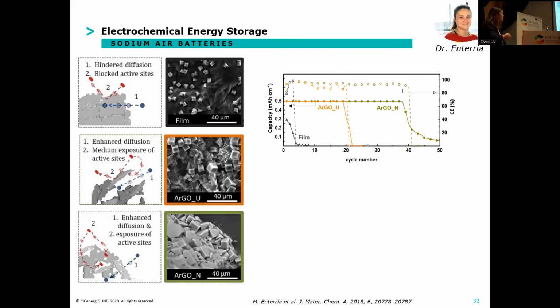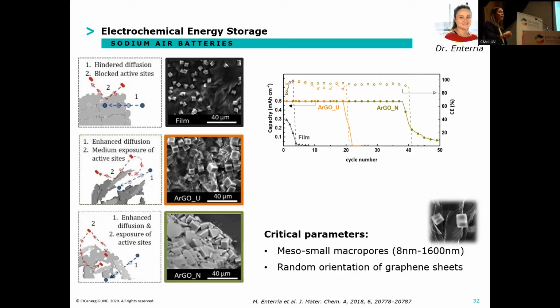And here also you can see really nicely how the sodium superoxide cubes grow, that in the one that has higher mesoporosity, all the surface is used. That's the reason it has higher discharge capacity. And also when you go to cycle this battery, the cycle number is also higher. So the critical parameters, we determined that it was the meso and small macro pore range, and also the random orientation of the graphene sheets.